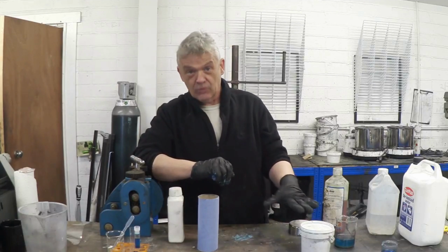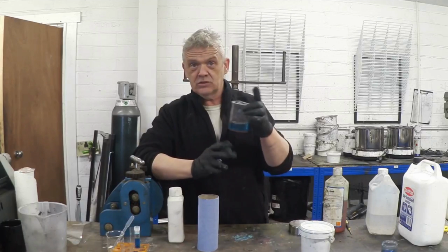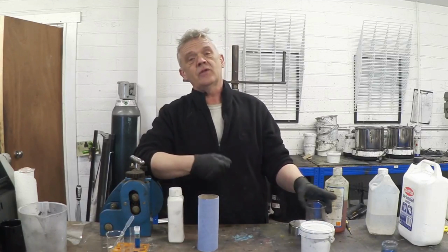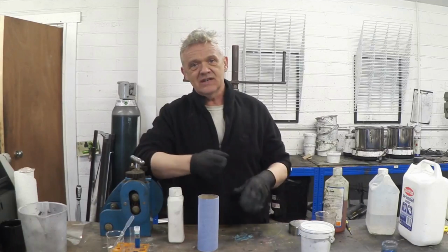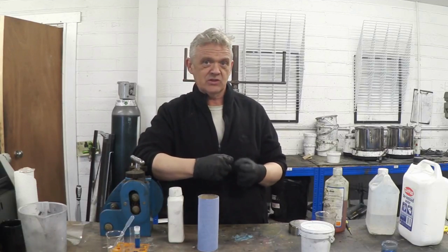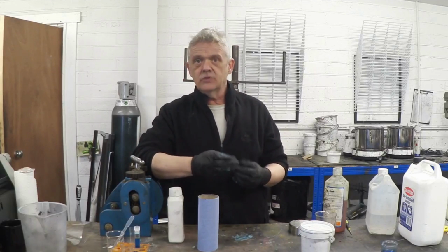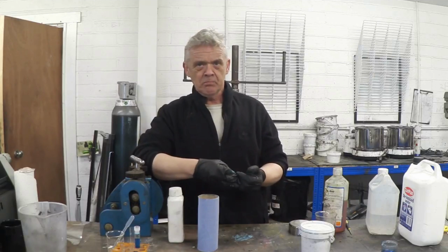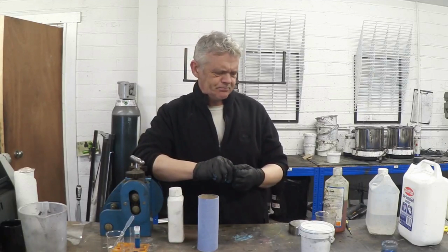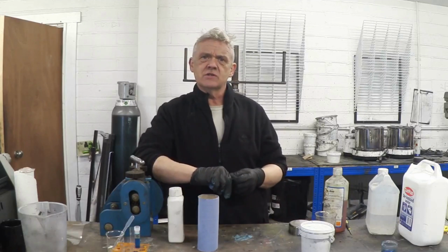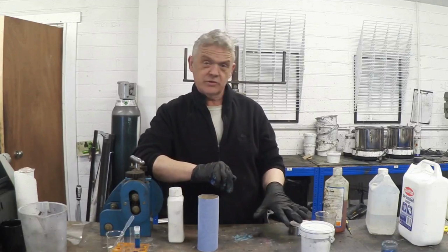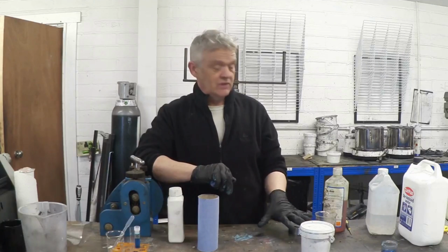But they're still extremely useful. We can decant that off or filter it off, collect those particles, and then you can use them to paint and anneal and make copper traces with them. It's quite a large scale, so you're using a paintbrush and that kind of thing. You're not going to be able to use a printer with it. But you can make copper traces from that copper material, which is soft, really, really easily.